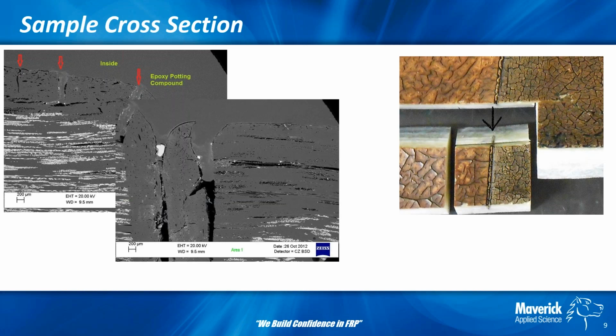So looking a little bit closer, here's a close-up of that joint area here. So you can see the potting compound coming down, and you can see basically the voids in the corrosion barrier where you can see the cracks. You can see where there was glass and now there's not. We're going to talk some more about that.